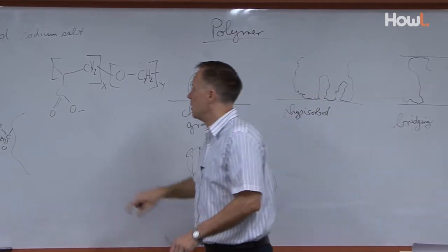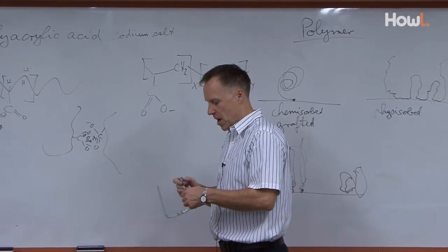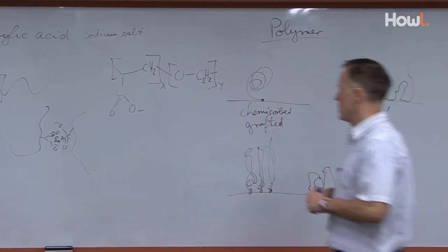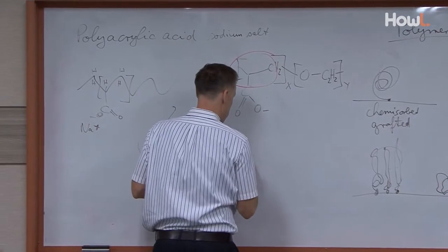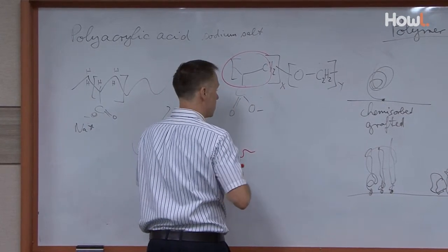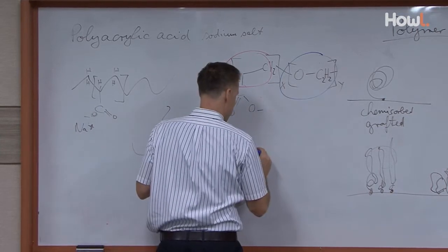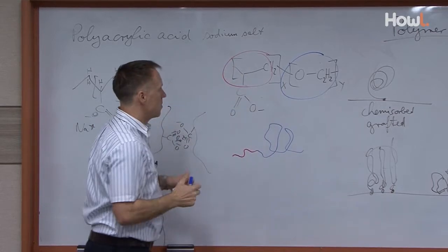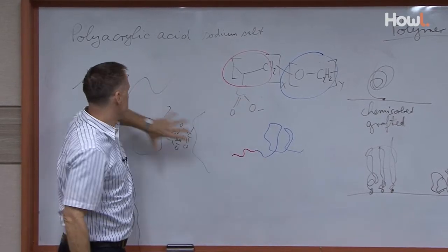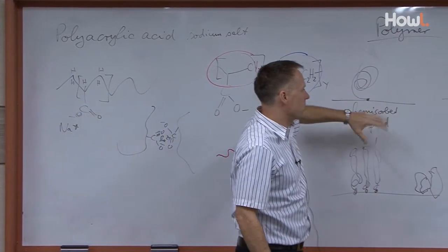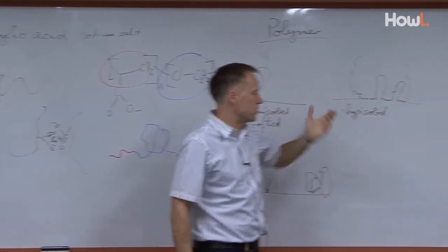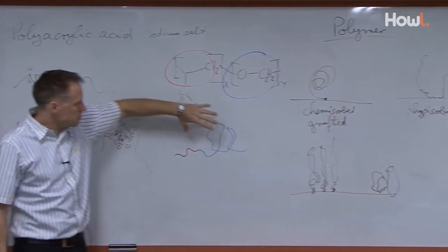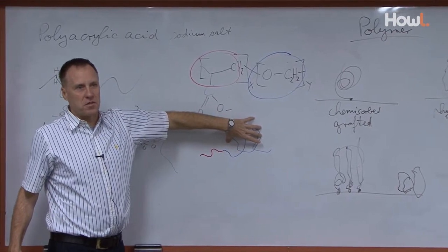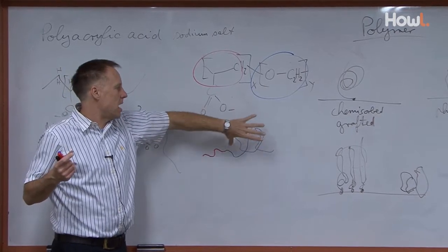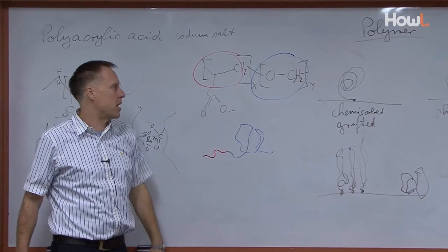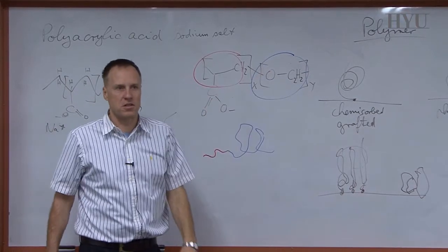And these two then form a compound that is basically, I turn this in red and the other one in blue. That is basically a short chain like this. And this part here is blue, a longer chain like this. Yeah? So this part here has still the features like this polymer, and it can anchor on the surface, a little closer to chemisorb or physisorb, basically, but physisorb here is a pretty good description. And this section here typically doesn't anchor so well on the surface. It could also adsorb, but it's not so strongly interacting. And the nice thing is it's much more independent from barium ions. Barium ions don't bind or complex to the oxygens in this molecule.